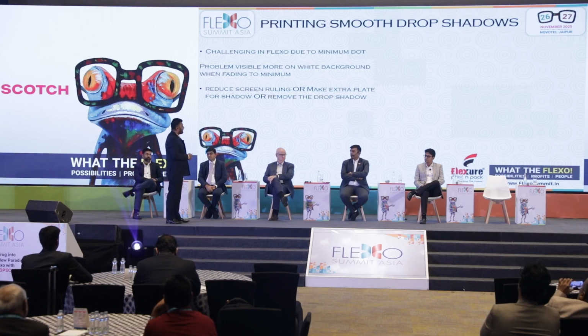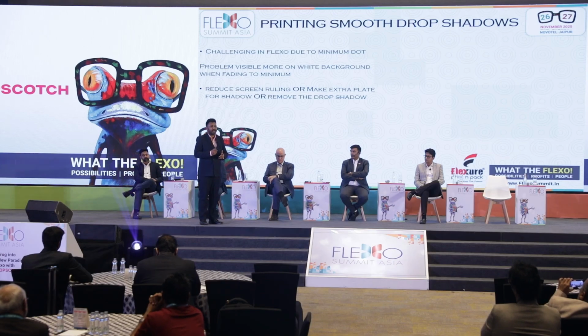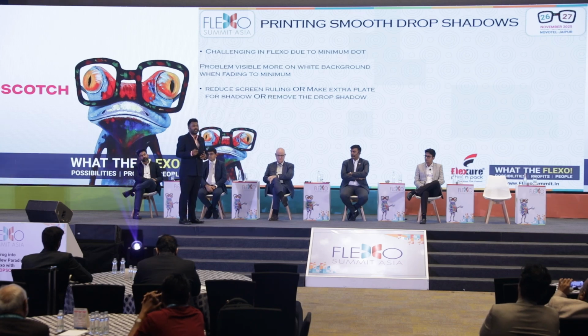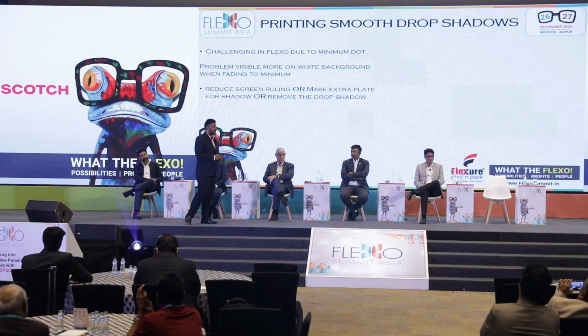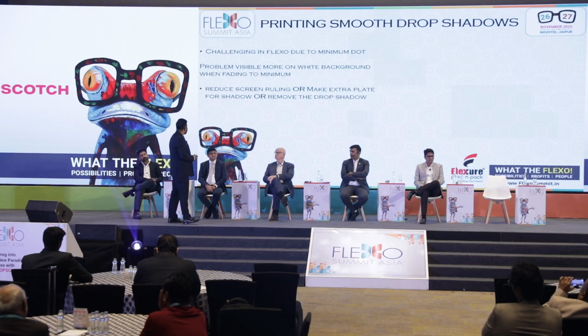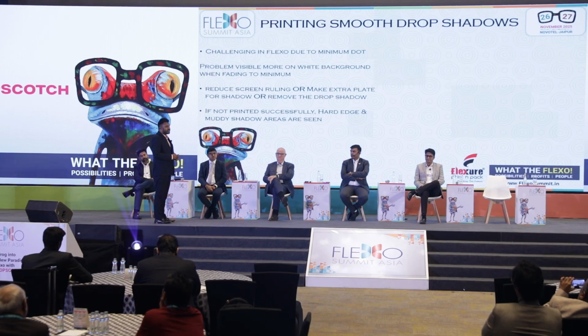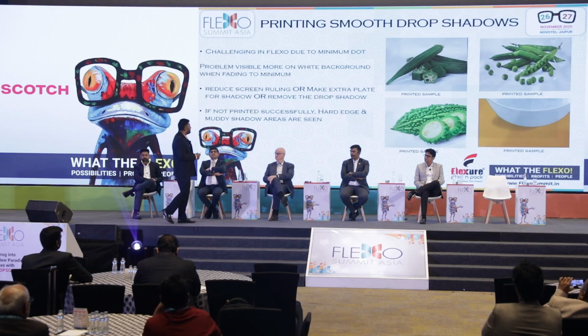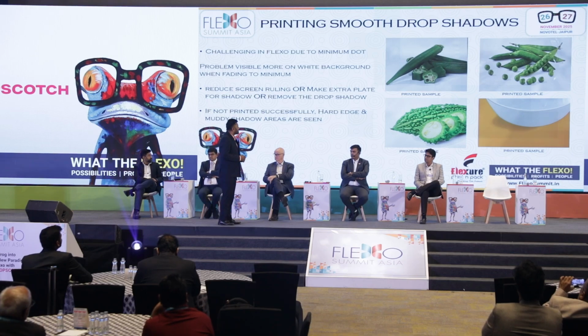So what do we do? We normally reduce the screen ruling so as to make sure that the dots are printed smoothly and they don't drop out, or we make an extra plate to print the drop shadows, or we remove the drop shadows. But removing the drop shadows doesn't solve the problem because the brand owners and the designers love the drop shadow. If they are not printed successfully, the hard edge is seen. So let us try to understand what is hard edge and ugly drop shadows. As you can see in the image, dots have gained in the tonal value and the hard edge and the muddy areas are seen.